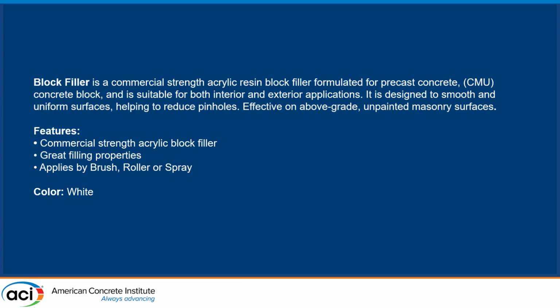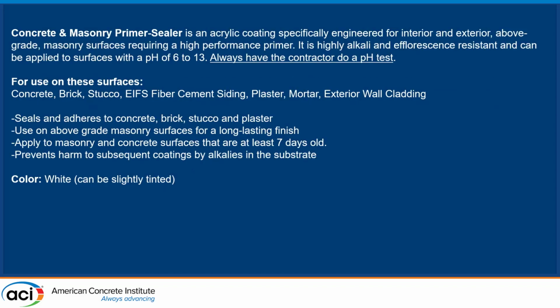Okay. So block filler is typically for CMU. This is a question I get a lot, when people want to put a block filler in tilt wall concrete. Block filler is very heavy in viscosity. It's meant to fill pinholes. You're worried about wind-driven rain coming through that wall, so you want a block filler to fill the pinholes of that CMU. Color is white. You can't really tint a block filler. Okay, moving on to the tilt wall primers.